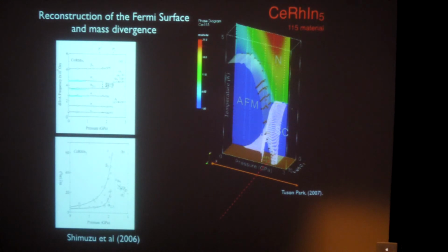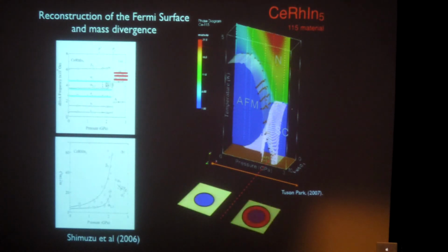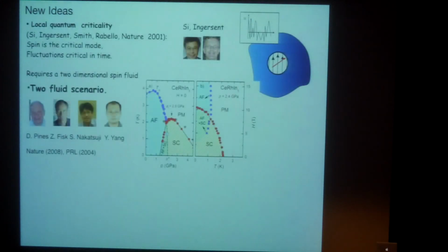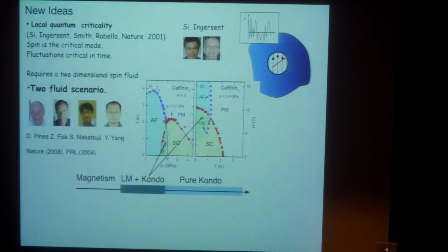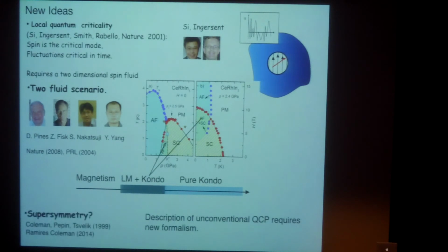And this jump in the Fermi surface volume measured by de Haas-van Alphen tells us that the local moments are delocalizing. We don't understand why. And it's led to a lot of new ideas, the idea of local quantum criticality, a phenomenological idea of a two-fluid scenario, and one that I'm particularly passionate about, the idea that we need new forms of wave function to span between magnetism and itineracy, and this requires a new formalism. We've actually been playing with the idea of supersymmetry.